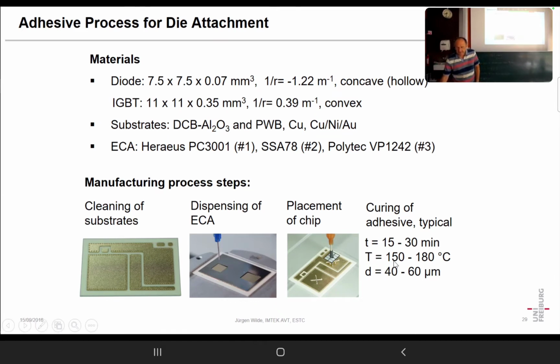So typical curing conditions, for instance, in that case, is 150 to 180 degrees centigrade. It is cured for 15 to 30 minutes. So you could say normally for the lower temperature, it's a longer time. And for the higher temperature, it's a shorter time. And here, for instance, we have a printing thickness of 40 to 60. Here you can say, as you do not lose material, the printing thickness will also be the final thickness of your bond. While in sintering, it is reduced by a factor of 2. And when you have solder paste, also the thickness is roughly reduced by a factor of 2 compared to the printing thickness.